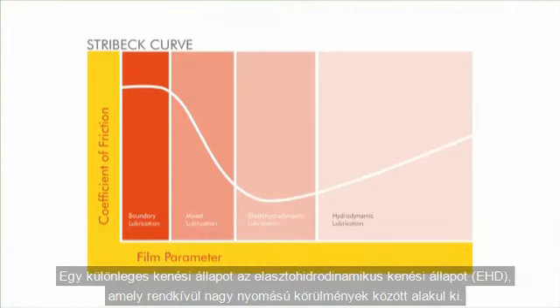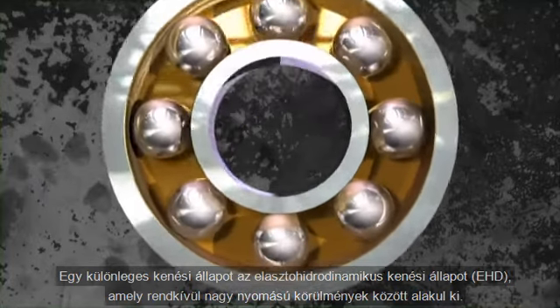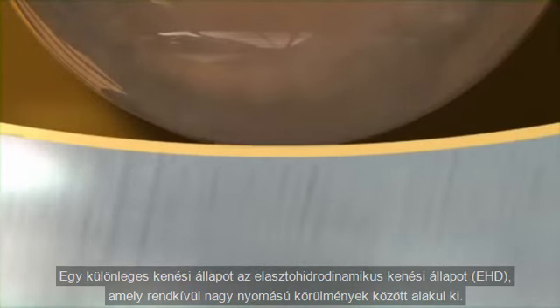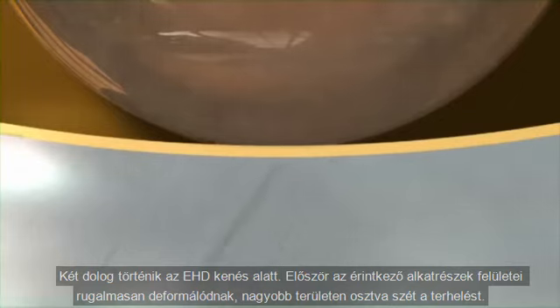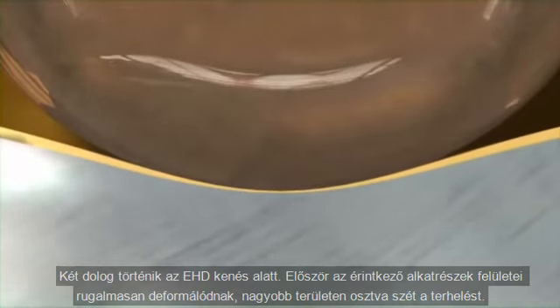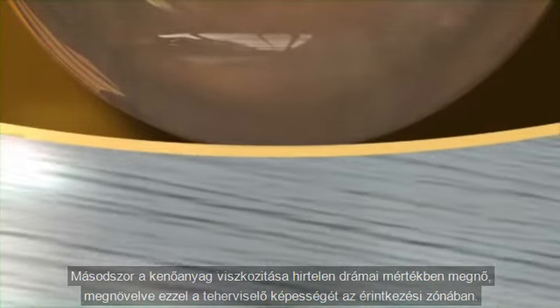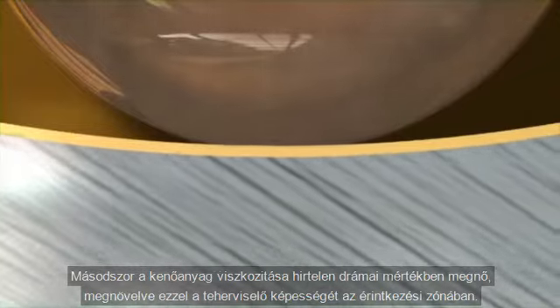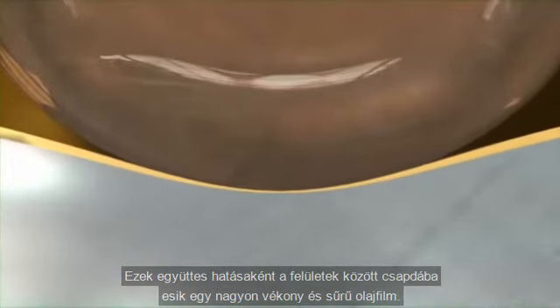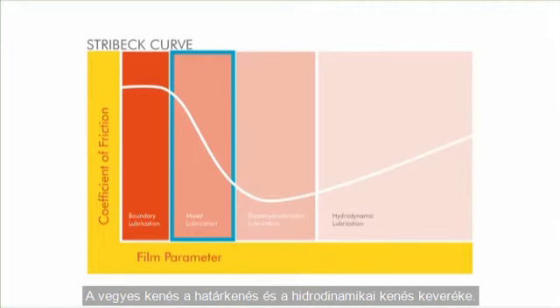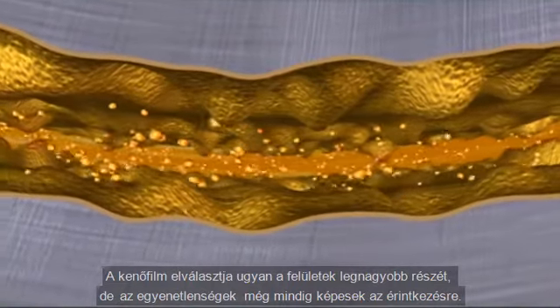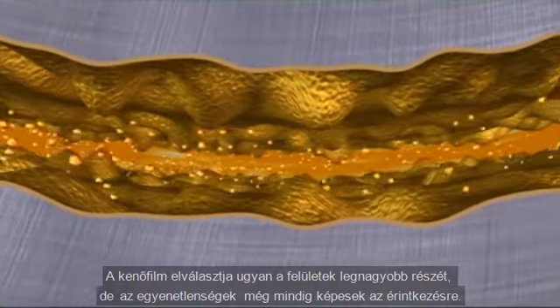A special kind of lubrication, elastohydrodynamic lubrication, or EHD, applies to conditions of extreme high contact pressures. 2 things happen in EHD lubrication. First, the surfaces of the contacting parts deform elastically, spreading the load over a wider area. Second, the viscosity of the lubricant momentarily increases dramatically, increasing its load-carrying ability in the contact zone. The combined effect is to trap a very thin but very dense oil film between the surfaces. As viscosity increases, sufficient hydrodynamic forces are generated to form a full fluid film and separate the surfaces. Mixed lubrication is a mixture of boundary and hydrodynamic lubrication. The lubricating film separates most of the surfaces, but the asperities can still make contact with each other.